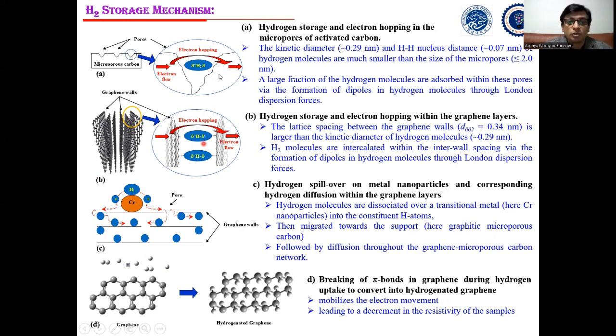The third reason is the hydrogen spillover on metal nanoparticles and corresponding hydrogen diffusion within the graphene layers. Generally, we know that in transition metals, hydrogen molecules are broken down and then spill over into this graphitic network, and therefore it absorbs more hydrogen. And finally, the formation of hydrogenated graphene from graphene, by breaking of the pi bonds in graphene during hydrogen uptake. Because of this fourfold reason, this system gives very high hydrogen storage capability, and therefore it can become a very good hydrogen physisorption material.